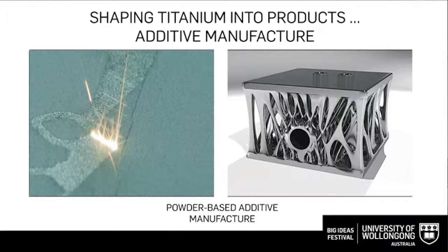A method that's very popular in the engineering industry is to take big pieces of titanium, usually formed as cast ingots or hot forged products, and then to machine away all the titanium that we don't want. So that is a subtractive process, and it ends up in a lot of waste. A more elegant process to form titanium is to use additive manufacturing, where instead of removing the metal we don't want, we build up a titanium component layer by layer.